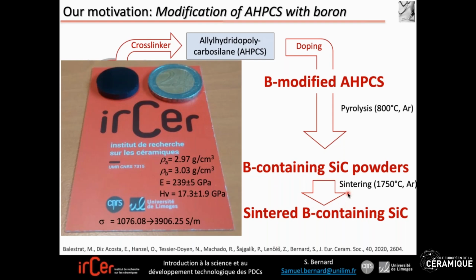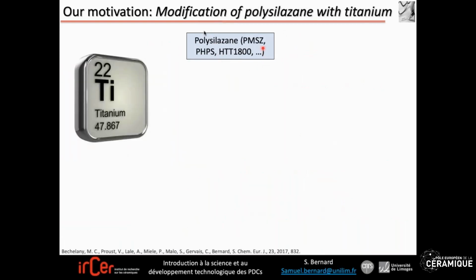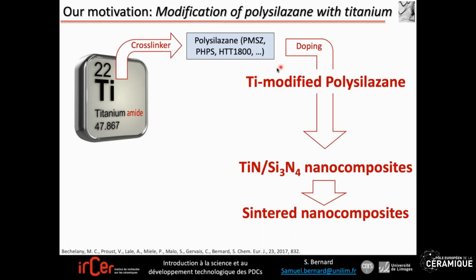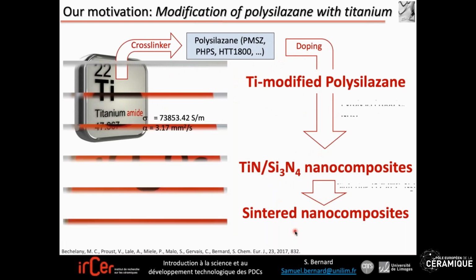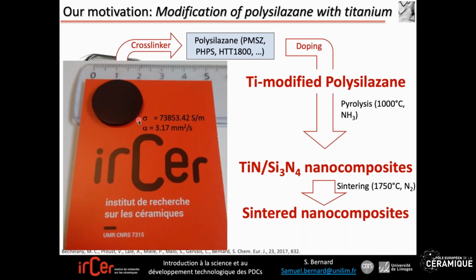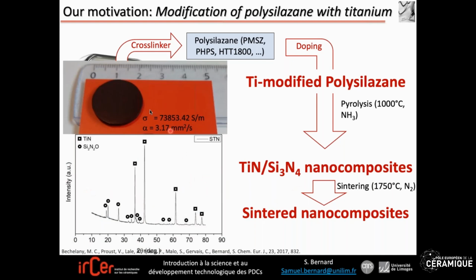You can use the same strategy, changing the nature and the composition of your polymer. You can use polysilazane. In that case, we add a titanium-containing precursor, titanium amide. The same process, we form our pre-ceramic polymers that can be directly pyrolyzed into powders to be sintered, and we form these colored pieces with an extremely high electrical conductivity because of the presence of titanium nitride nanoclusters, which are dispersed in a silicon nitride based matrix, as you can see on this XRD pattern. So here we form nanocomposites with a very high electrical conductivity, the highest of the PDCs materials. And these materials are very interesting because you can also control the color of your materials through the quantity of titanium nitride nanoclusters you use in your materials.